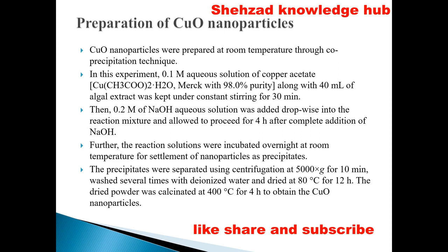Then 0.2 molar NaOH aqueous solution was added drop-wise into the reaction mixture and allowed to proceed for 4 hours after complete addition of NaOH. Further, the reaction solution was incubated overnight at room temperature for settlement of nanoparticles as precipitates.